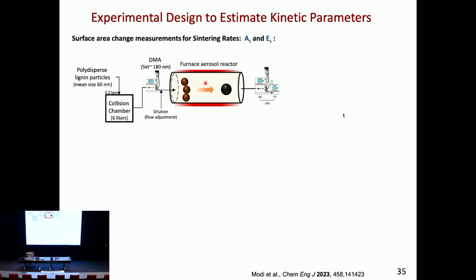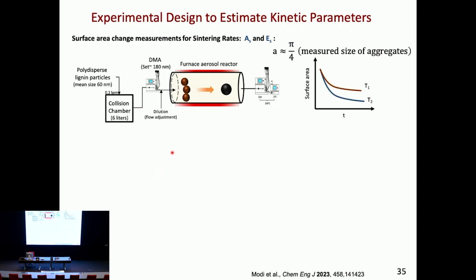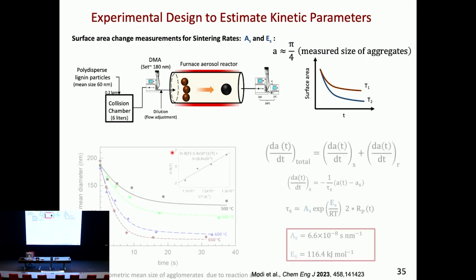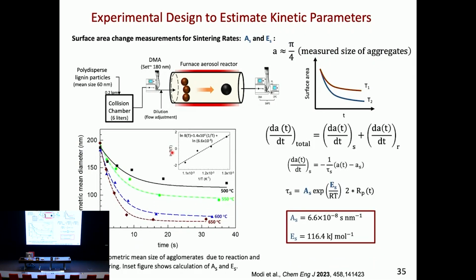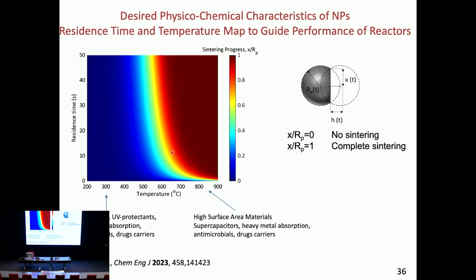Prior to entry into this furnace reactor, I have a collision chamber so that I can create some of these agglomerates and so forth. And I plot the change in surface area with time. Again, I fit an expression to get the characteristic time and some of the Arrhenius parameters for sintering. So a very fundamental set of measurements which gives me this, and I'm just going to put it all together now.